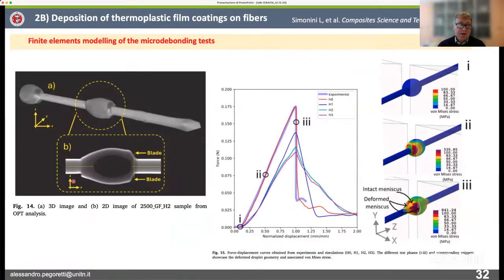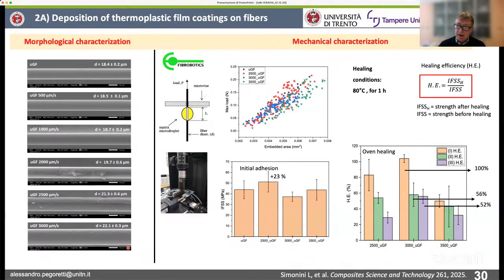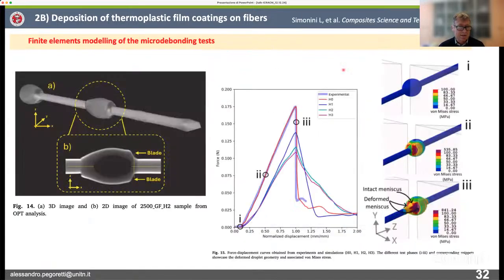What we did observe is that after the first healing, the droplet actually changes the geometry, of course, because it is in contact with the blade, so the geometry changes. And this change in the geometry is not taken into account in our calculation. So if I go back just a minute, in this calculation of the healing efficiency, we assume the same shape of the droplet. So we did not take into account the fact that each time we are repairing the interface, we have to test it, and therefore we are deforming the droplet.